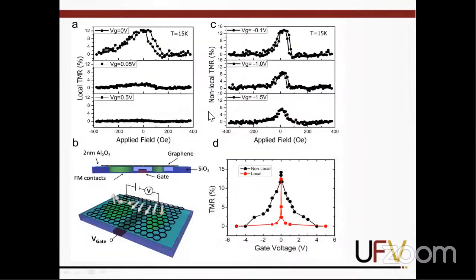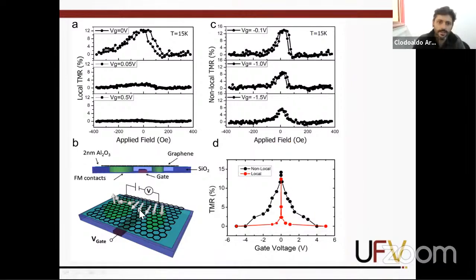So then we were able to apply gate voltage in this transistor to check if it works like a spin FET. And then we saw that when we have a local configuration, the voltage kills the spin current very quickly. And in a non-local configuration, that killing is not so sharp and is a little bit broader. Then we conclude that using local configuration is the best solution because we need just 2 contacts, and also we can kill the spin polarization with a very low voltage. This is interesting for our application.